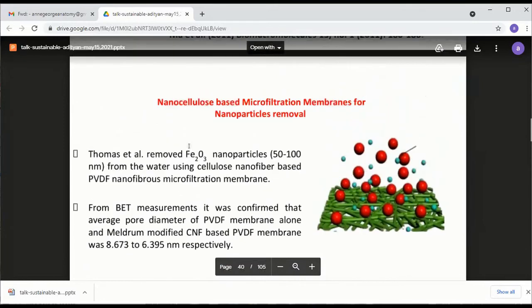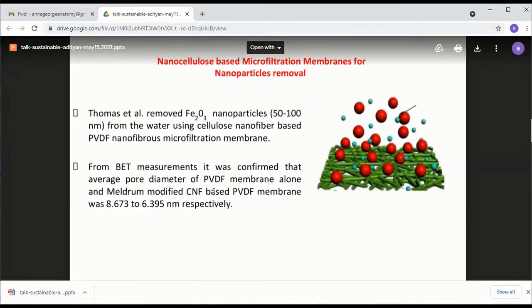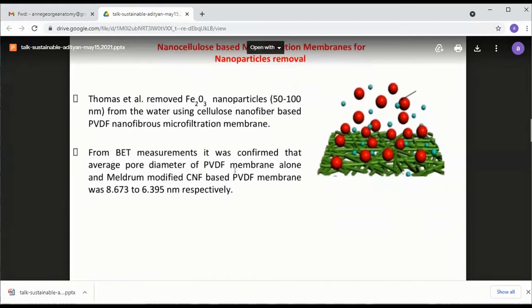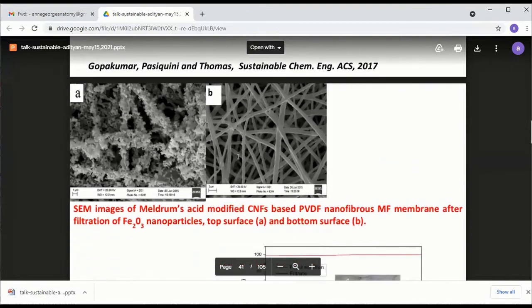Dear friends, I'm going to show you another important work. Again, water purification. Probably you all know that water has a lot of suspended particles. It could be iron oxide, it could be other suspended particles. We try to remove this using the same protocol. So we have used this filter, and the pore diameter of this filter is in the range of 8 to 9 nanometer. And when you try to separate out these suspended particles, you see, this is the filter after the filtration process. All the suspended particles were retained at the top of the filter. They're all iron oxide. See the bottom part of the filter, very clean.